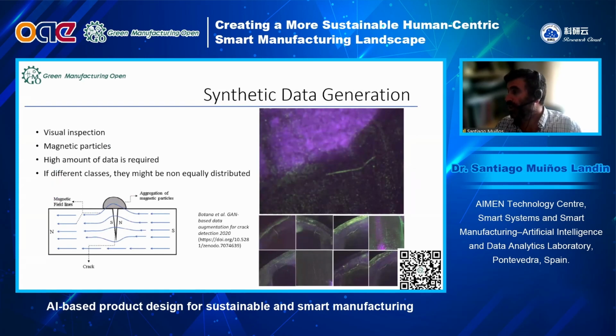And one quite intuitive application that we found was the generation of synthetic data for defect detection based on images, when we did not have enough data to train our network to reach a given performance. For instance, it happens from time to time that you have different typologies of a defect. For instance, here in this image, you can see a crack. This is an image of a crack of a metallic part in the manufacturing of an automotive part, a part of a car.